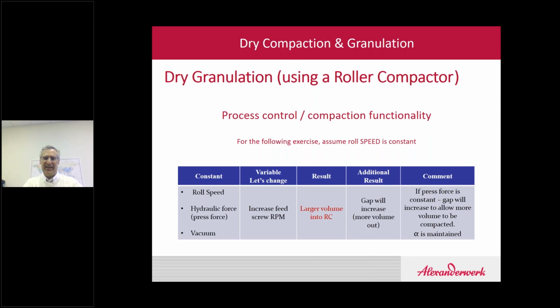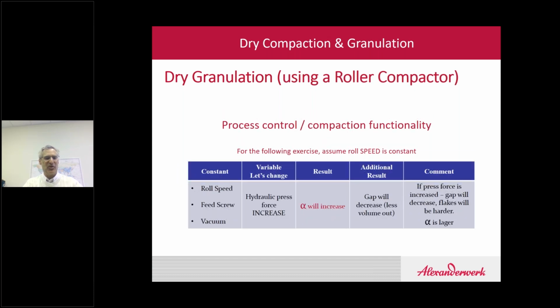And what actually happens at that point is, since the gap increases, but the hydraulic force is constant, my alpha, my compaction force, is still maintained. Remember, on the Alexanderwerk roller compactors, the top roll typically floats and the bottom roll is fixed. Let's take a look at another example. And this is again process control.